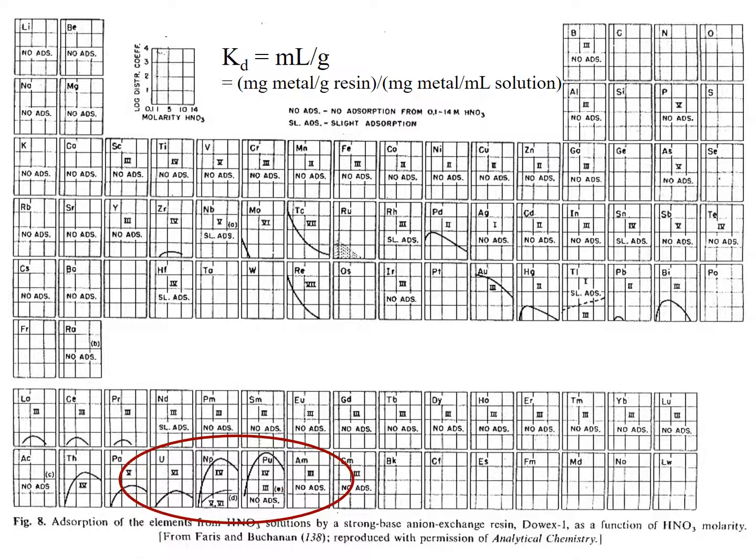For the actinides, we see sorption that peaks and decreases. Again, for plutonium, plutonium-4 has strong sorption, plutonium-3 has no sorption, neptunium-4 strong sorption, neptunium-5 and neptunium-6 limited, uranium-6 not as much as plutonium. So the tetravalents here seem to be strongly sorbed, whereas the others are weakly sorbed.